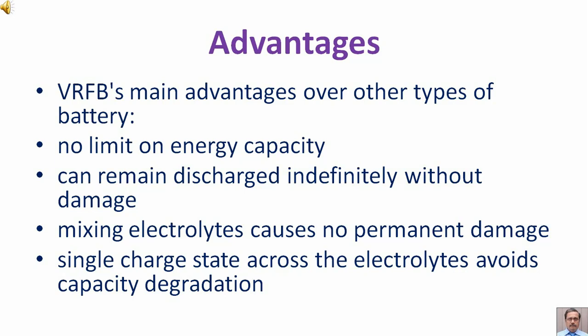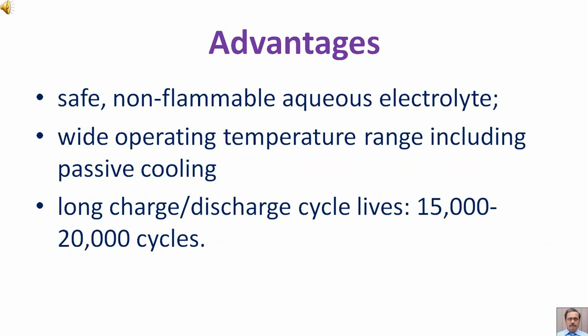Advantages: VRFB's main advantage over other types of battery: no limit on energy capacity, can remain discharged indefinitely without damage, mixing electrolytes causes no permanent damage, single charge state across the electrolytes avoids capacity degradation, safe, non-flammable aqueous electrolyte, wide operating temperature range including passive cooling, long charge-discharge cycles lives 15,000 to 20,000 cycles.